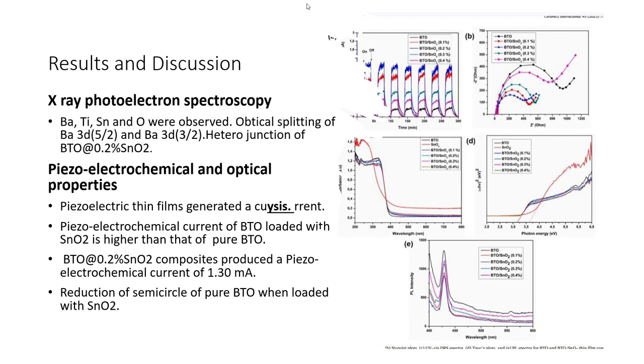Next, we are going to discuss X-ray photoelectron spectroscopy. The Ba 3d profile on the figure confirms the presence of barium, and the Ti 2p profile on the figure confirms the presence of Ti4+, and the Sn 3d profile on the figure confirms Sn4+ presence. The key findings are the heterojunction formation between barium titanate and tin dioxide, indicated by higher binding energies. The shift in peak position suggests changes in electronic structure due to SnO2 loading.